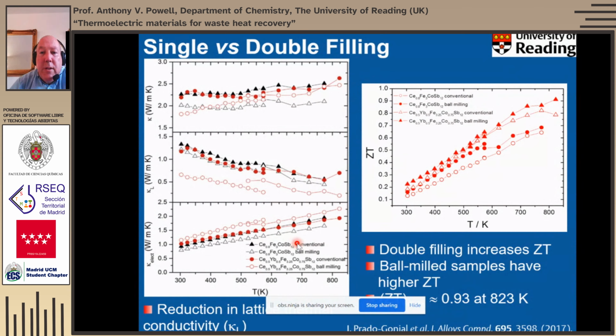So that was what we set out to achieve, and that's then reflected in the ZT values here, because we can see, unfortunately, we've now changed our symbols. So now the double filled are the triangles, and we can see that the performance of the triangles, whether made by conventional processes or by ball milling, is significantly improved over that of the single filled materials, and we get a maximum ZT of about 0.93 at 823 Kelvin. So that seemed to vindicate the strategy of saying, well, what happens if we use more than one filler, and we aim to introduce ions, rattlers with different vibrational frequencies? It does indeed give improved performance.